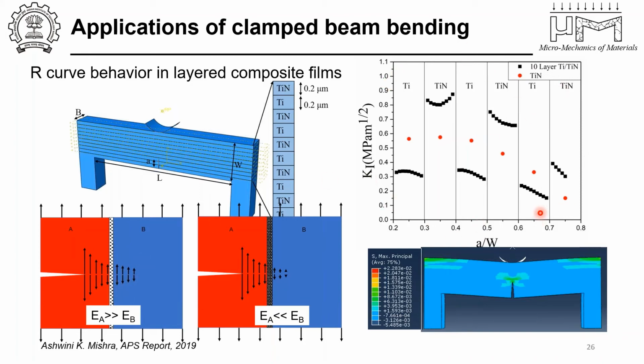So this is what we could record. This is from simulations, and we are in the process of doing experiments to measure them. This shows that as the crack moves from the Ti to the elastically stiffer TiN layer, there is a drop in the stress intensity factor. But then again, when it goes through the TiN layer and approaches the Ti, there is an increase in the stress intensity factor. This is the K1 for a single layer of TiN, if it was a monolithic sample, whereas this is the case for a multi-layered sample. So there is a substantial difference in K1, or the driving force for crack growth, that one could record if you have this particular geometry.